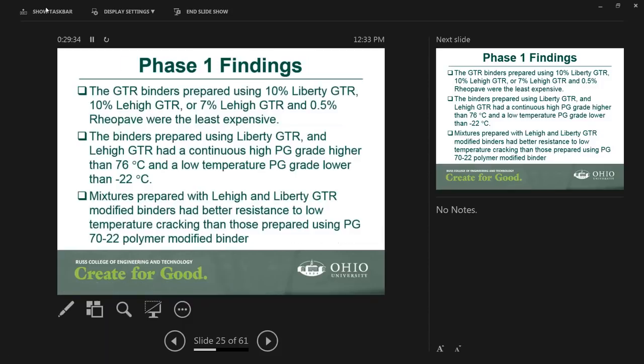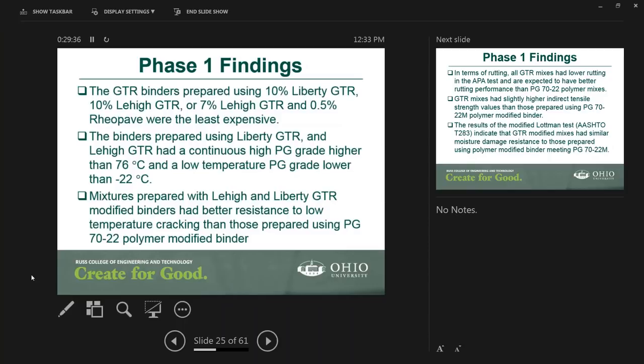So to summarize the phase one findings, basically the lab study, we have found that the mixes prepared with the GTR binders, all three GTR binders, had a slightly better resistance to low temperature as well as fatigue cracking as compared to a polymer modified binder meeting the 70-22.